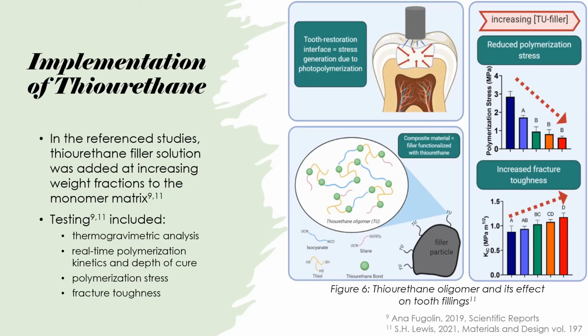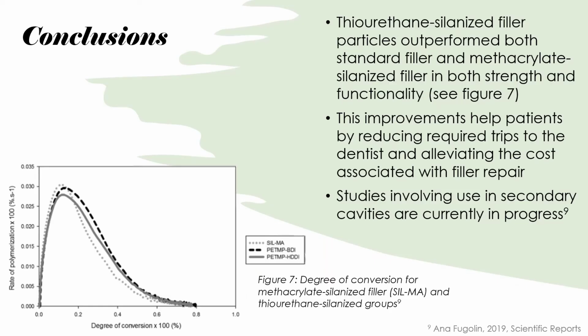As seen in the graphs on the far right, increasing weight fractions of thiourethane filler led to lower polymerization stresses and increased fracture toughness. As demonstrated in these studies, thiourethane not only outcompeted standard filler, but alternative approaches such as methacrylate silanized filler as well. Thiourethane presents improvement in not only the aforementioned mechanical properties, but degree of conversion for a given rate of polymerization as well, as seen in the figure on the left.